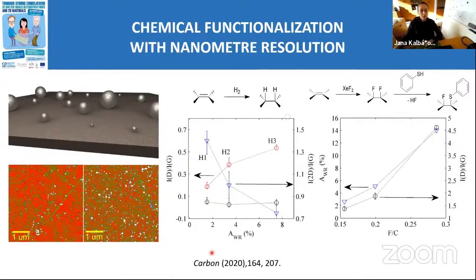So if somebody is interested, I can come to it in discussion. But nevertheless, with increasing amount of corrugation, we also observe that we can introduce more hydrogen and fluorine on the sample. In other words, it's in fact something which we would expect.